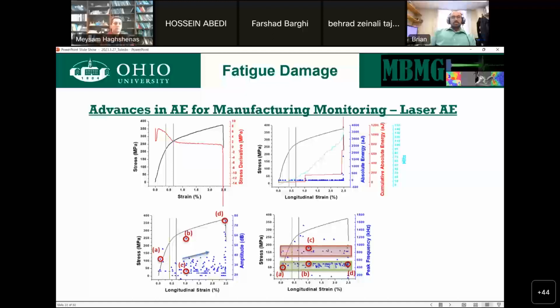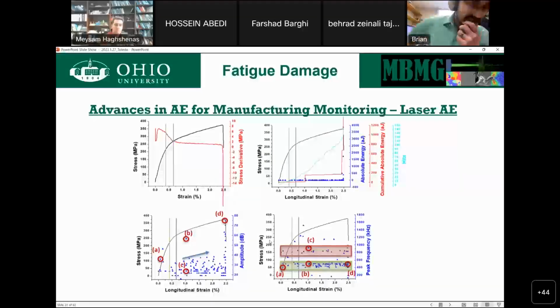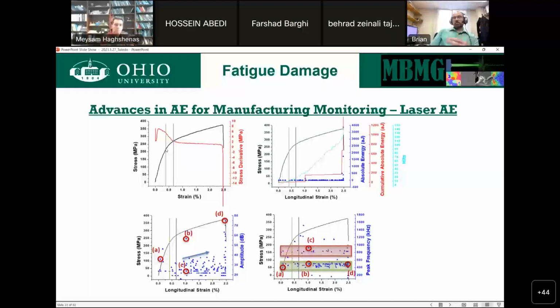But we're not limited to just fatigue tests, to monotonic, to load, to doing this by hand. We can see that separation. We see trends as they're happening, but we can really zoom in on certain effects. So looking at the AE, we can see with load curves, there's a change where the yield's happening. We can see a lack of activity before, only a little bit. We can see a growth of activity after. We can start to connect how the material is responding with only using sound. We're just listening to this material as it deforms.